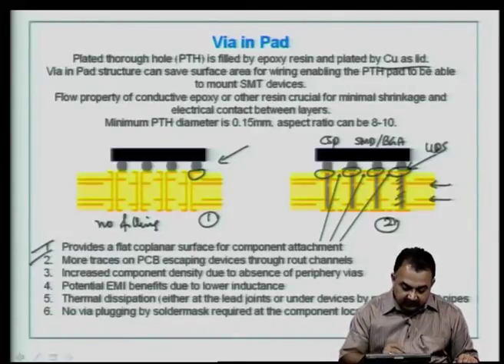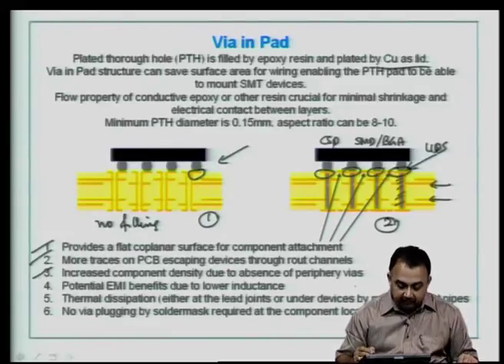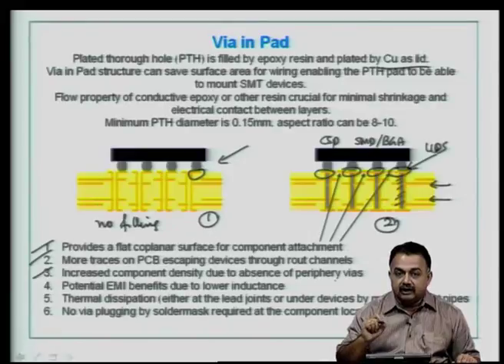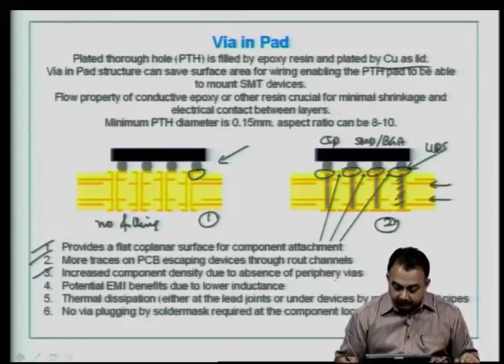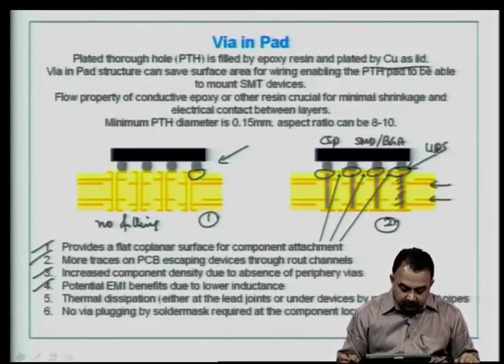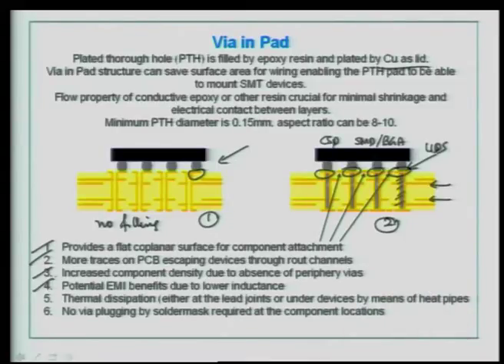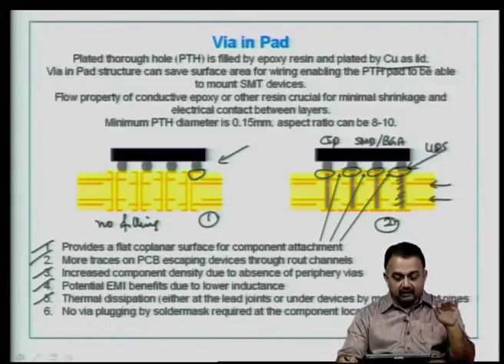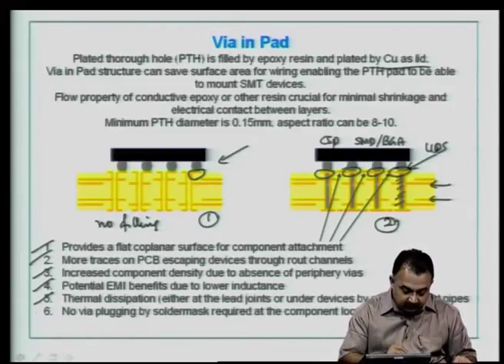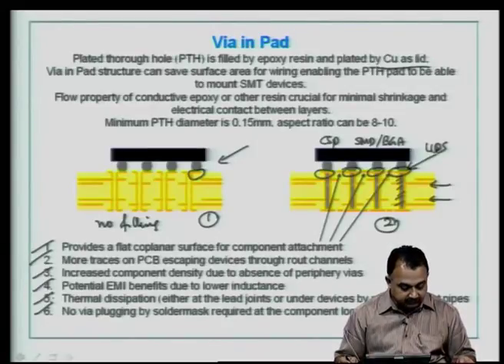Increased component density due to absence of periphery vias, potential EMI benefits due to lower inductance, because if you look at the contact point between the BGA solder ball and the pad, it is almost a very low interconnection length, therefore, there is low inductance. Thermal dissipation either at the lead joints or under devices by means of heat pipes. So, these structures act as heat pipes, and no via plugging by solder mask is required at the component locations. Otherwise, what you do is you plug the area with a solder mask material. So, here you are using a conductive paste to perform that function.